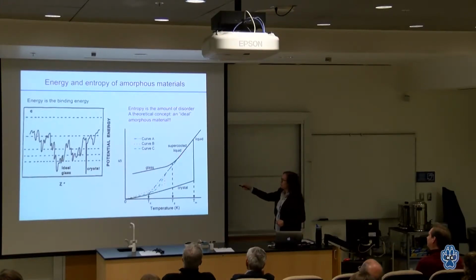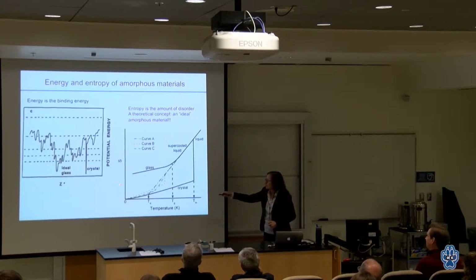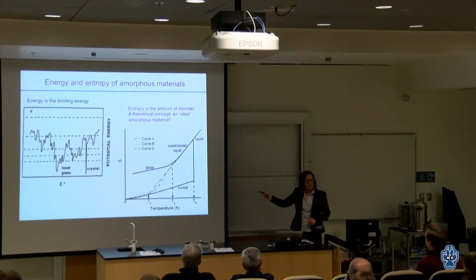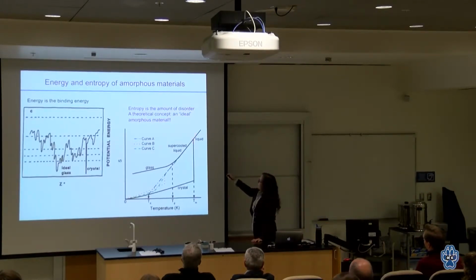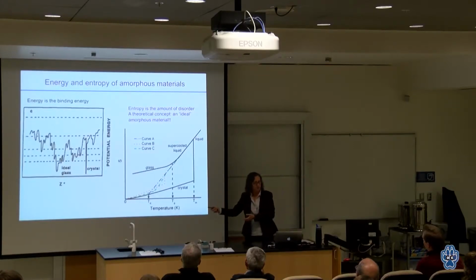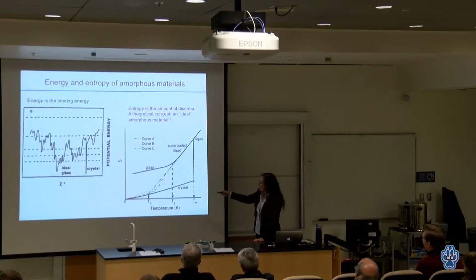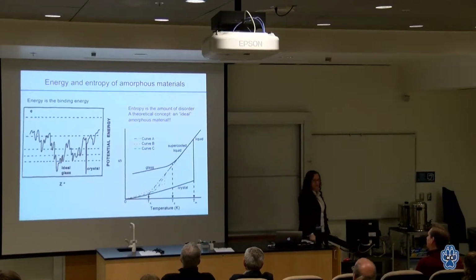If I cool more slowly, I can follow that line further. If I wait longer, I can follow down that line further. And what happens is we get a whole family of curves, depending how fast I cool, like that. What a man named Kauzmann realized quite a long time ago is that you cannot do this experimentally. When I'm talking about cooling more slowly, you hit the point where it's beyond the lifetime of the universe. Nonetheless, you can extrapolate that line, not worry about the fact that it has to be beyond the lifetime of the universe. And what you'll find is if you extrapolate that down, you hit a temperature at which the entropy of the liquid is the entropy of the crystal.